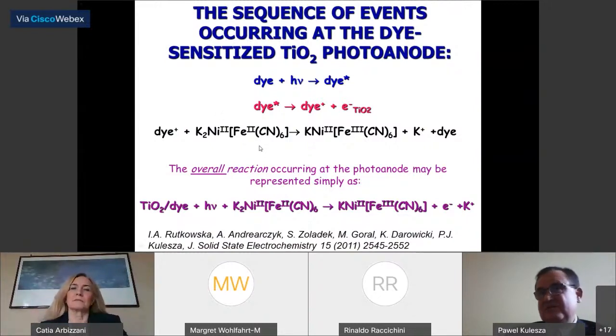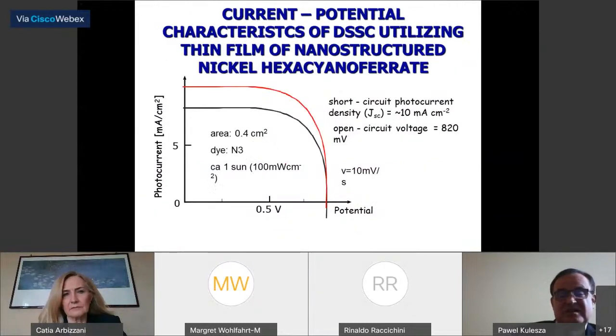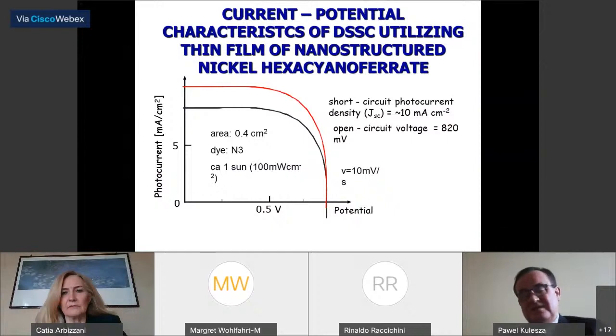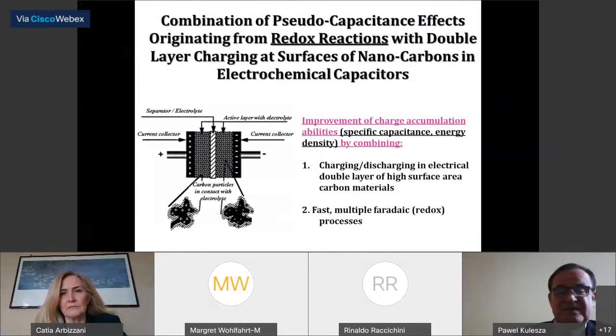And the mechanism is similar to the iodine iodide couple because we actually reduce oxidized dye using the iron 2 cyanoferrate part. And we can regenerate the system upon illumination. So we basically can go to pretty high potential output. It was not great, perhaps, the current density, at least it was done a number of years ago, but the potential output was better than for the iodine iodide system. Of course, this research is more fundamental than practical because it's difficult to control the degree of hydration.